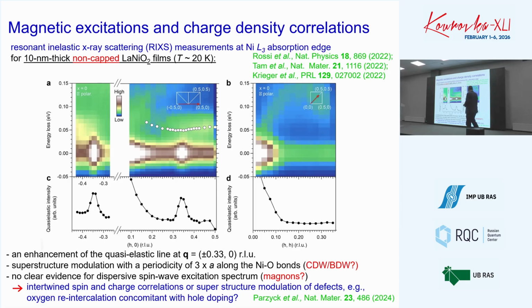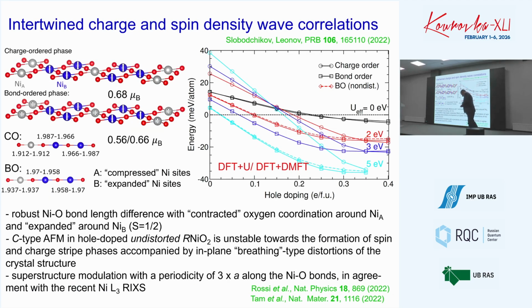Although nowadays this result is somewhat in question, a possible explanation is that due to the synthesis there is some kind of long-range superstructure modulation due to oxygen. Oxygen defects tend to order in the lattice, and because of this ordering there is some quasi-elastic peak here, which in the beginning was claimed to be the formation of the CDW phase.